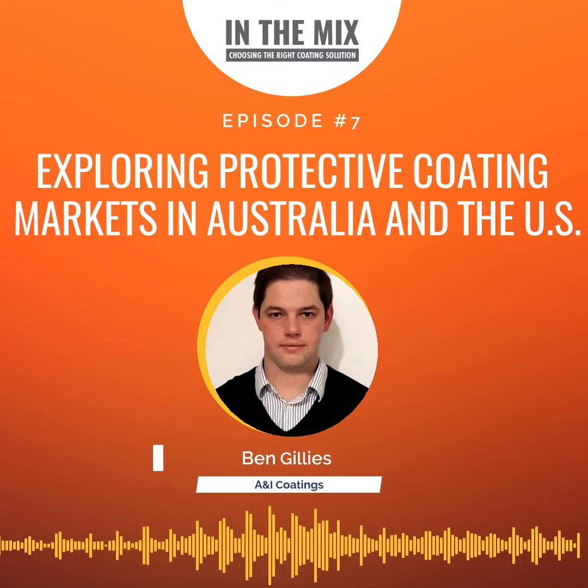Initially with polyurethane, but then 100% of the production was switched out to use a fluoropolymer top coat, which was Vitreflon 700. So it's kind of the two companies went hand in hand. Okay. A&I Coatings made the paint and supplied it to Vitreflon, which put it on the facade panels. And that was where a major portion of our fluoropolymer sales would have gone to in the early days. Now it's kind of flipped. The compressed fiber cement is, I guess, a much smaller percentage of our overall market.